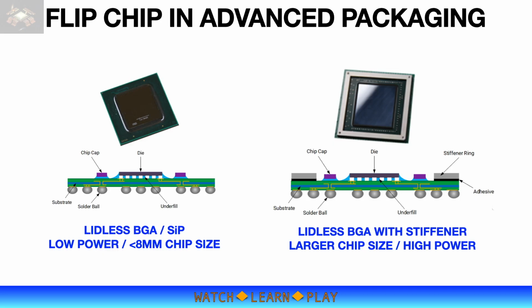However, more advanced chips are larger, and larger die sizes exhibit greater package warpage due to the difference in thermal expansion between silicon and laminate materials. As a result, large die lidless BGA is more difficult to solder mount and may produce larger variations in bond line thickness between the die and external heatsink. To address the warpage issue, a stiffener ring around the periphery of the package substrate is added to provide structural rigidity.